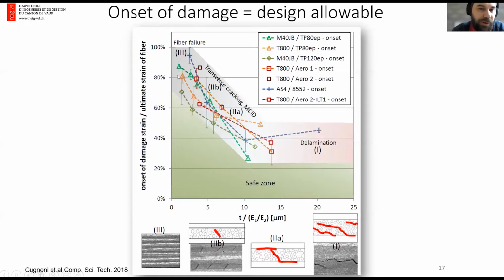But for the thinnest ply here, about 30 micrometers per ply, we can reach very high values for the onset of damage, and for the best systems, nearly 100% of the potential of the fiber. This means that with thin ply, you can actually use the full potential of the fiber you paid for, which is, I think, a good sales argument, even if I'm not a salesman.